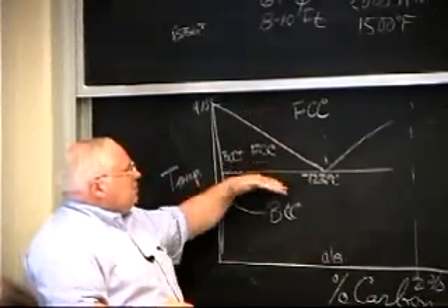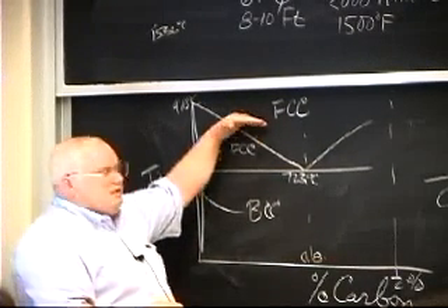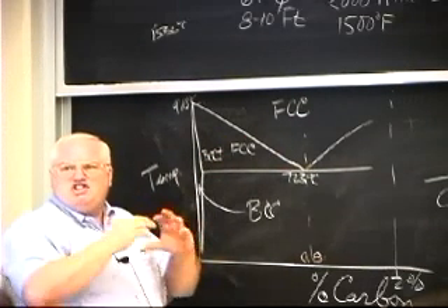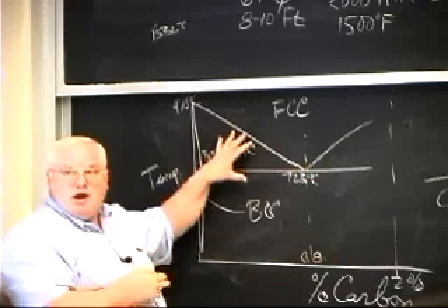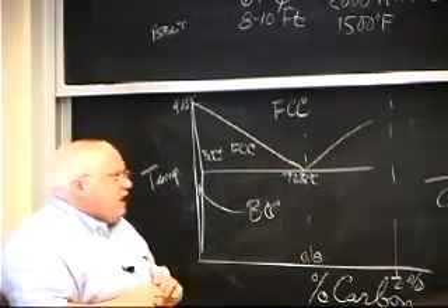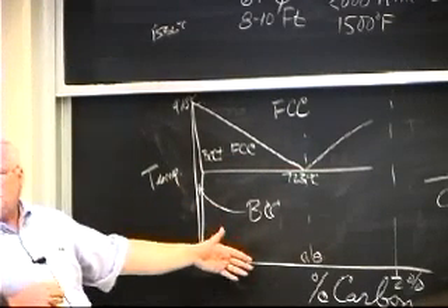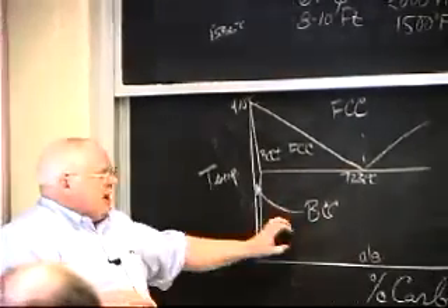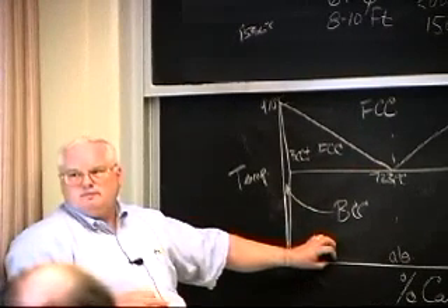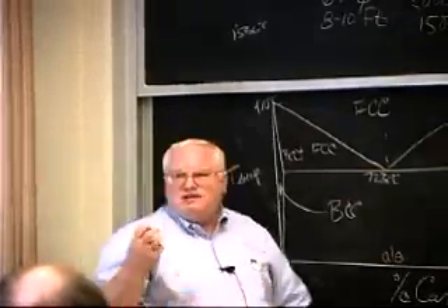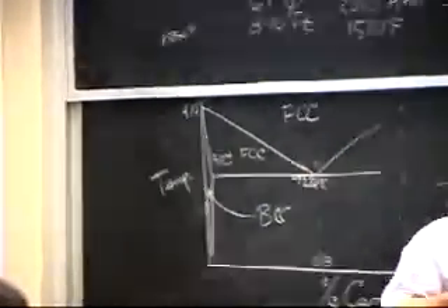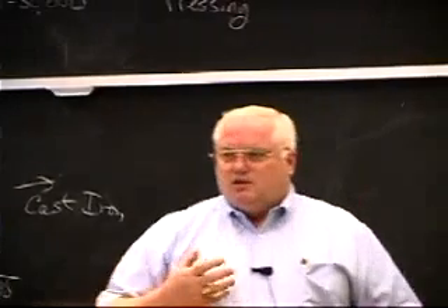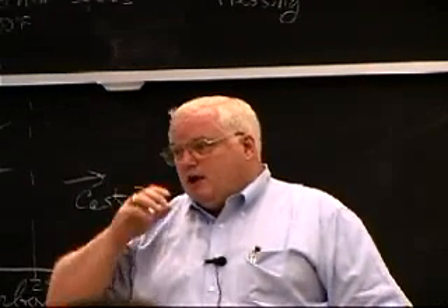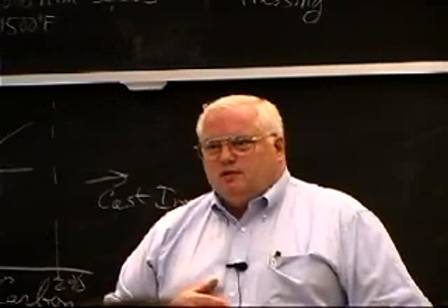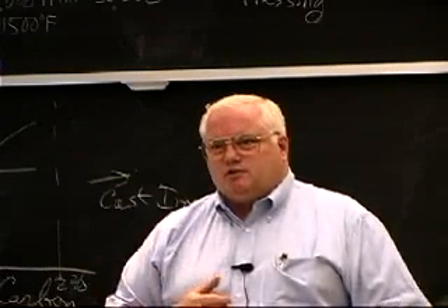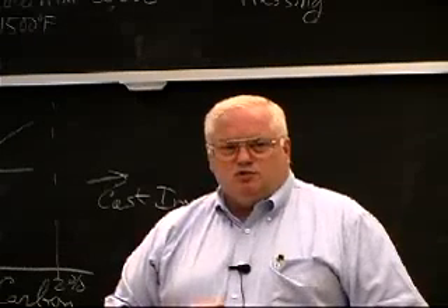But if I cycle between these crystal structures and allow the material to change and form new grains, and I do it the right way, and I also deform the steel at the same time, and I cool it down when I'm all done more rapidly than just letting it air cool, I can end up with very, very fine grain size. I can end up with grain sizes where the grain volume is 1,000 times less than it would be for typical old steel that you would build a building out of. And that steel can have double the strength and 5 times the toughness of the type of I-beams that you usually build a building out of.